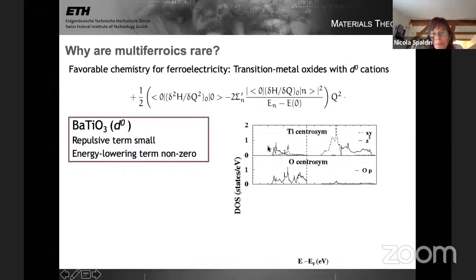So again, here's the case of barium titanate, the prototypical ferroelectric, and I'm plotting the density of states as a function of energy, still in the centrosymmetric structure. What you see is that the top of the valence band is made of oxygen 2p states, and so it has odd parity. The bottom of the conduction band is made of titanium d states, and so it has even parity. Because I'm hybridizing between oxygen and titanium states, this matrix element is non-zero, and I have a large energy lowering when I make my distortion.